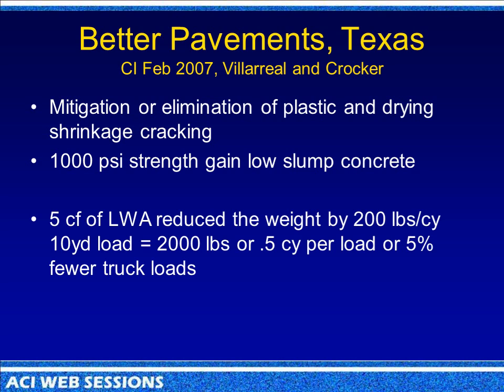And one of the sidebars is, 5 cubic feet of lightweight aggregate will reduce the weight of that mix 200 pounds. So if you have a 10-yard load, that's 2,000 pounds. Well, that's a half a yard of concrete. And down there, they were running 10.5 yards of concrete out. So they were using 5% less trucks just by doing an internal curing thing. See, that's common sense. There's no rocket science about this stuff.